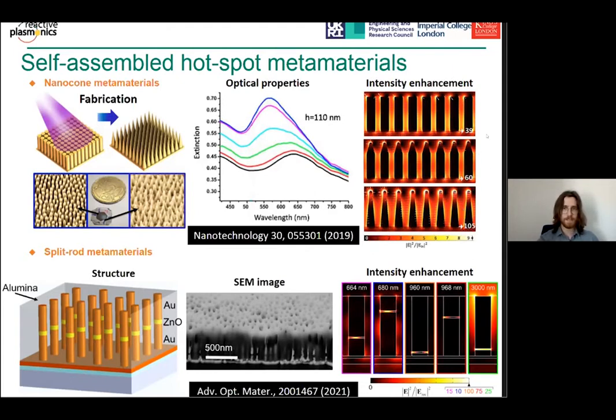And we see that this intensity enhancement is concentrated at the apexes, at the tips of the nano cones. And we can tune this by changing the shape of the materials. We can also tune it by changing the spacing of the materials as well.